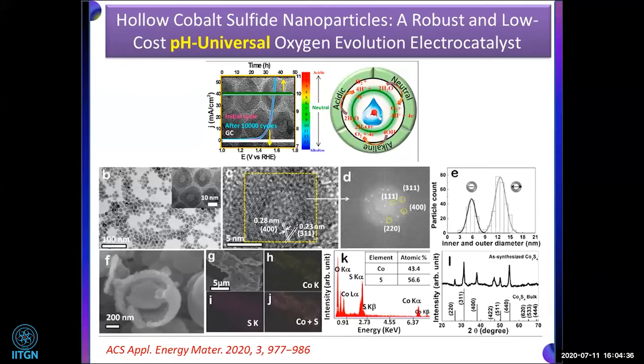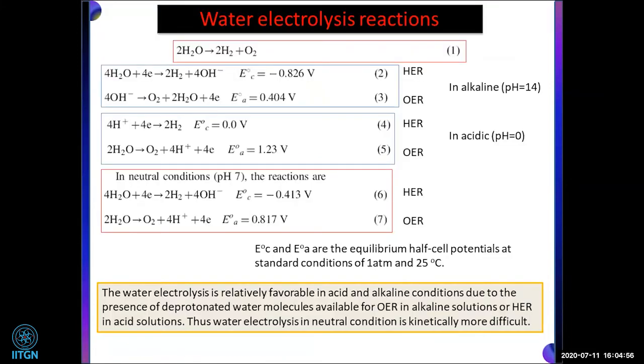The formation of this hollow nanoparticle happens because the cobalt was first nucleated, and on addition of sulfur it leads to oxidation of cobalt from the core, which comes out and reacts with the sulfur, forming the cobalt sulfide shell outside the hole. This we already know. Water electrocatalysis is relatively favorable in acidic and alkaline conditions due to the presence of deprotonated water molecules available for the OER. But this is difficult in the neutral condition, which is kinetically more difficult.